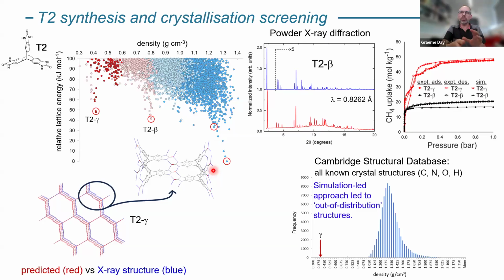There's solvent in those pores, and when we pull the solvent out, if we do it gently enough, you end up with that porous structure. But the structure is inherently metastable. And so if you start to do things with it, like putting in methane, taking it out, and cycling this process, it does eventually convert to the lower energy structures. So what we actually want for porous materials is something where you have porous materials which are the global minimum, so there's nowhere for them to go in terms of down in energy.